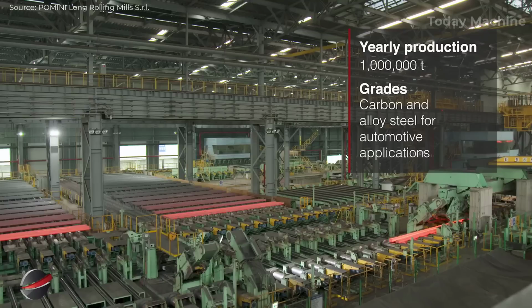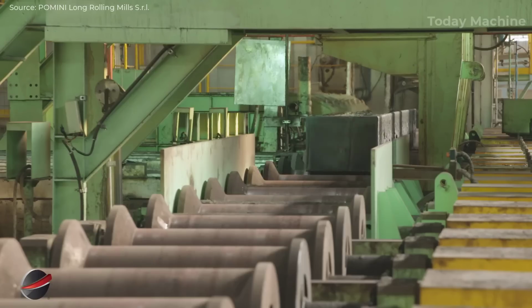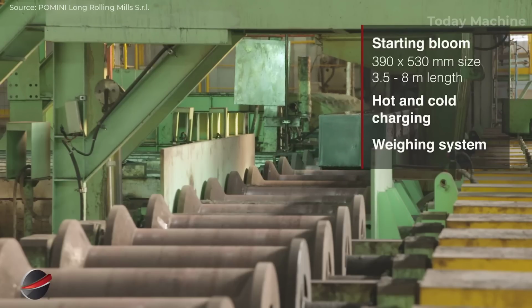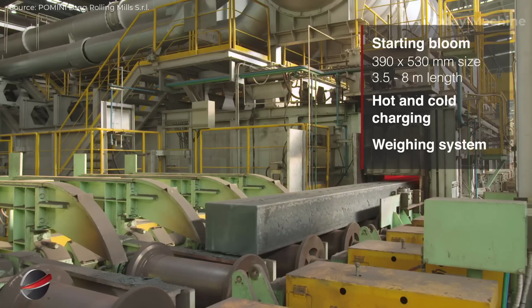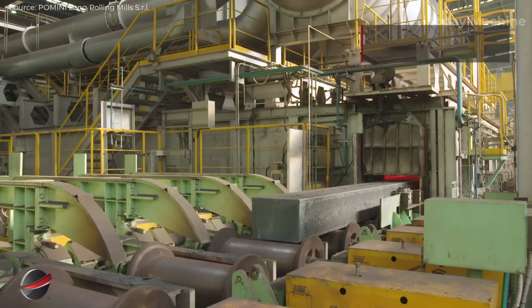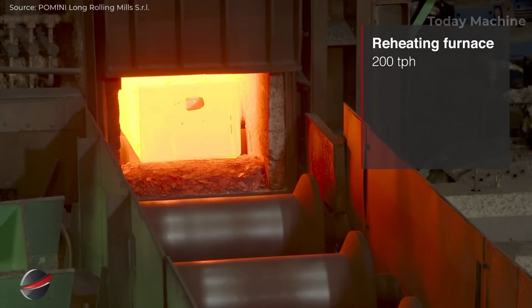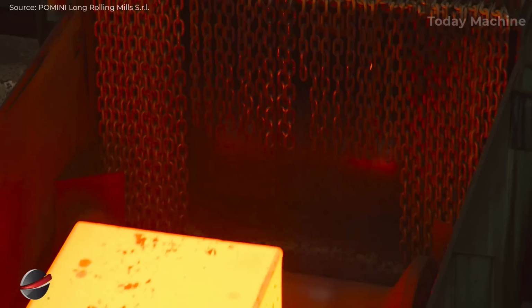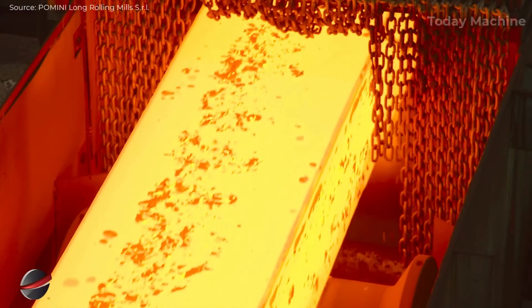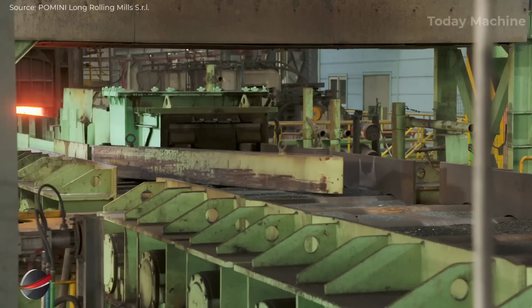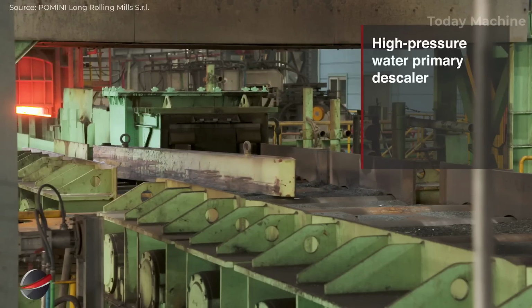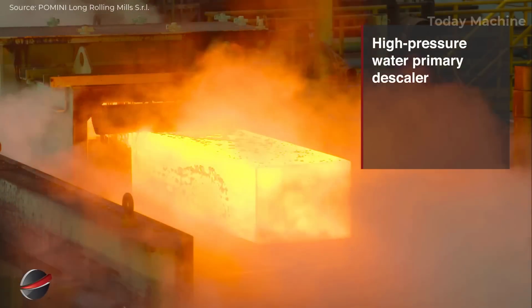The large bar mill at Hyundai Steel's Dongjin plant is a state-of-the-art facility, producing up to 1 million tons of carbon and alloy steel each year, mainly for automotive applications. The process begins with the charging of blooms into a reheating furnace that has a capacity of 200 tons per hour. The blooms are heated to the required temperature and then descaled using a high-pressure water primary descaler.